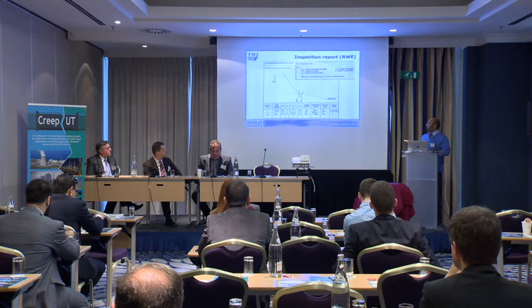So when the client was given a report, they were given this report. So you had clearly a surface breaking flaw about 5 to 7 millimeters in depth, and clearly it was not deemed to be critical, this particular flaw, because it hadn't traveled very far. But as Alex pointed out, the problem is that very often it starts from the inside and moves outwards. And so there is the possibility that it could travel to lead to a full fracture before there is any evidence of it on the surface.